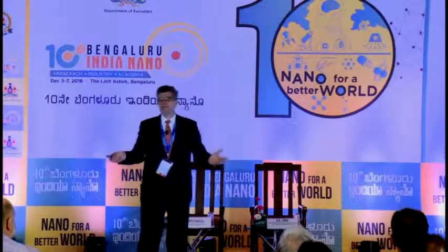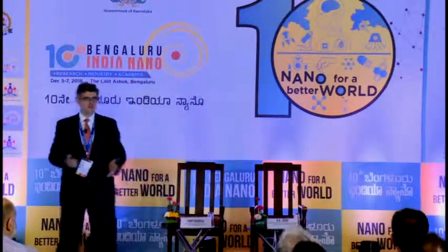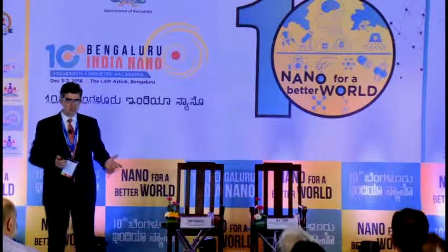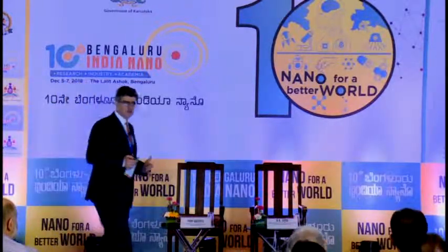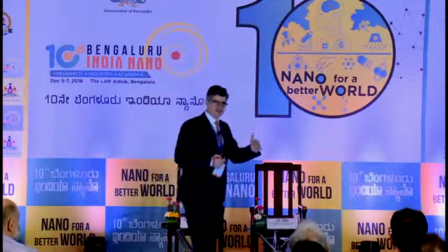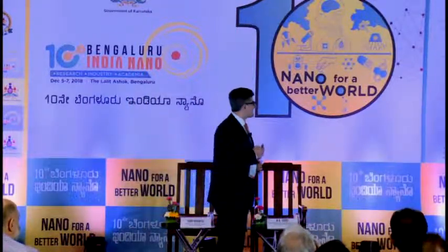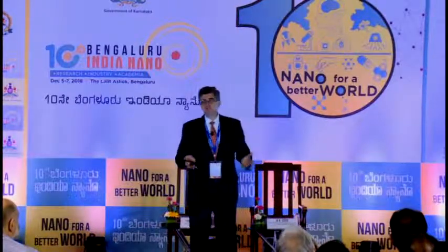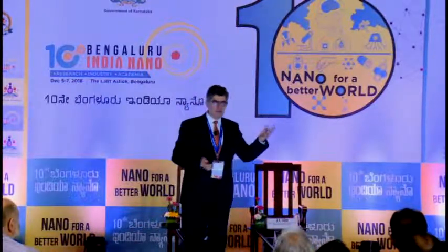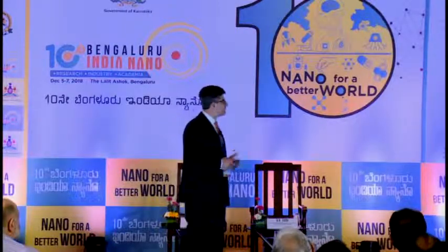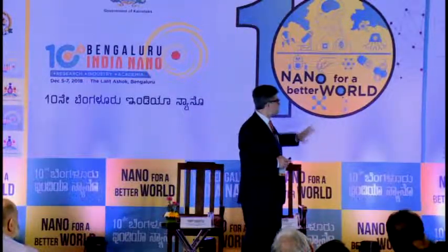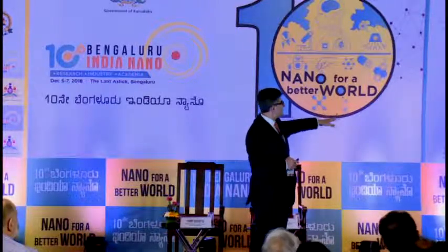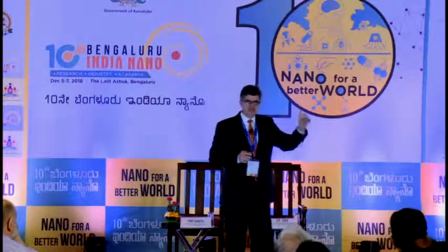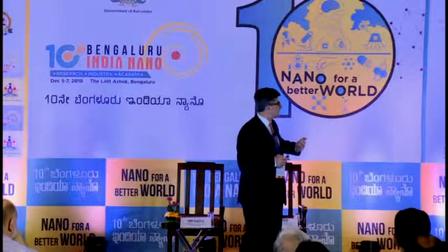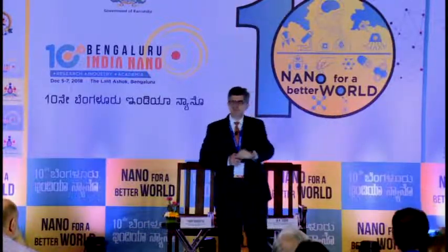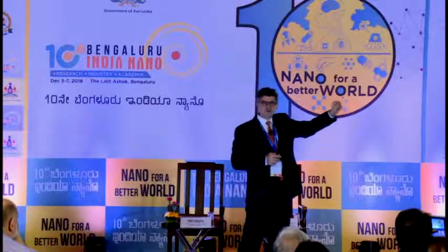And what the community is doing, it's not only us. Research in MXenes is going on in more than 40 countries now. Actually, the number of publications from China is already about 3 times higher than the number of papers from the US. And we're exploring properties step by step here. For example, we showed that these flakes are very, very strong. You can see here Ti3C2 monolayers and bilayers we tested compared to perfect graphene. The trick is here, you can see graphene and boron nitride have the 2 highest bars, but those were produced by peeling off perfect single crystals.